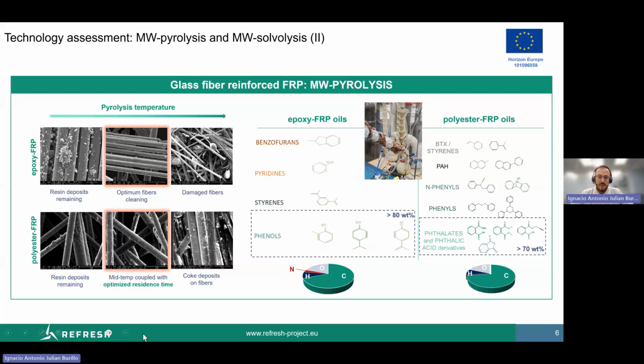Regarding the oils, the ones from epoxy can get up to 80% in weight of phenols, mainly p-cumylphenol or BPA, that are the chemical building blocks of the epoxy itself, so they can close the cycle towards the production of new epoxy resins. In the case of polyester, what we get is phthalate and phthalic acid derivatives that represent more than 70% in this case. But if we look at the atomic composition, carbon, hydrogen, oxygen, nitrogen, the composition of these oils would be also suitable as fuels, as precursors for fuels.